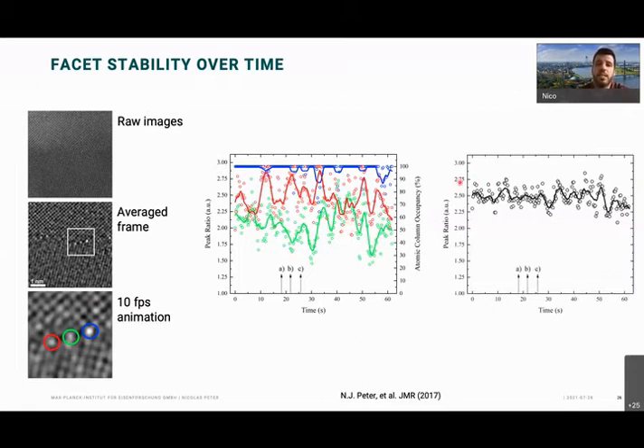And that again means that silver is pretty much staying in the facet and doesn't like to go out or doesn't like to take up more. So once the facet is there, it's pretty stable. And this is now no temperature, this is just induced by the electron beam. We give energy to the grain boundary by the electron beam, 300 keV.